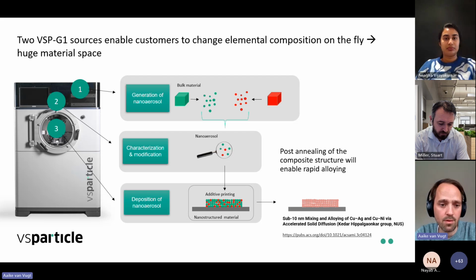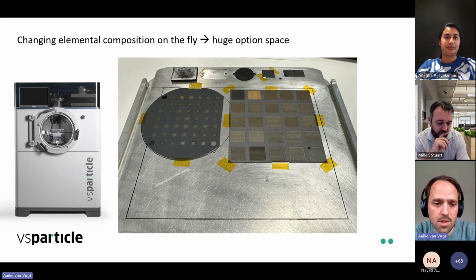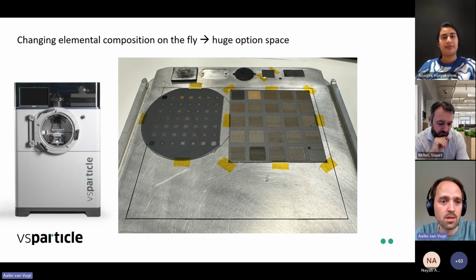It is the best process that I've seen so far in the inorganic material space to do high throughput synthesis of combinatorial materials. And I can show you an example of samples that we have been printing on a weekly basis. So here we have used two different materials, and every square that you see on the silicon wafer is a 2 by 2 millimeter, 0.25 milligrams per square centimeter loading of unique compositions. And we have printed the same compositions on the silicon wafer and on the GDE. So this is done for XRD analysis to really verify the formation of a new phase or this new alloy. And the GDE substrates are then used for electrochemical testing. This is for CO2 electrolysis.